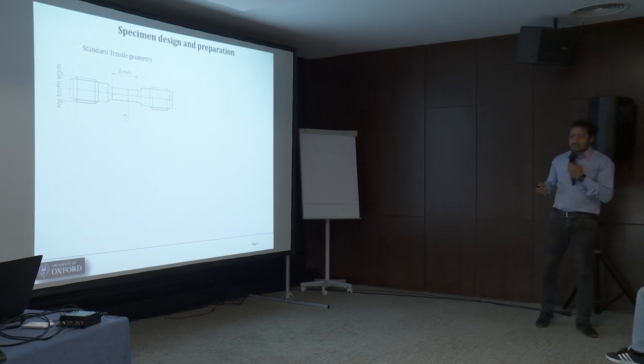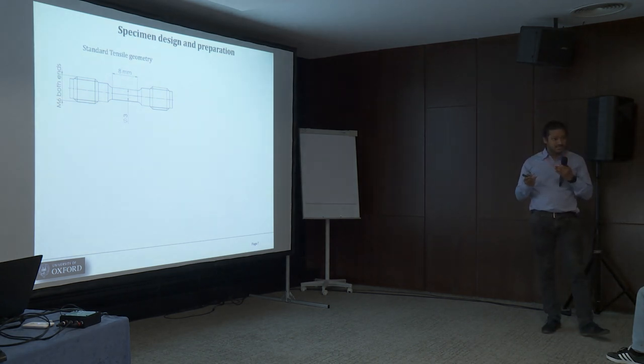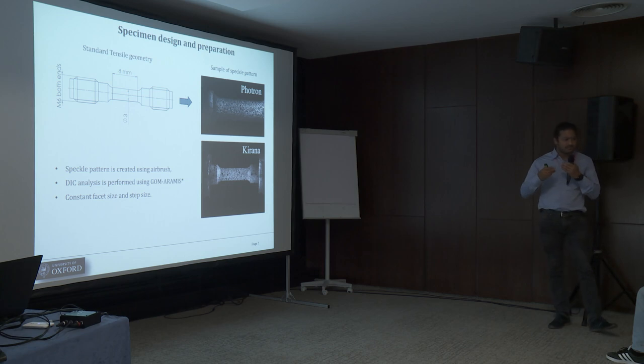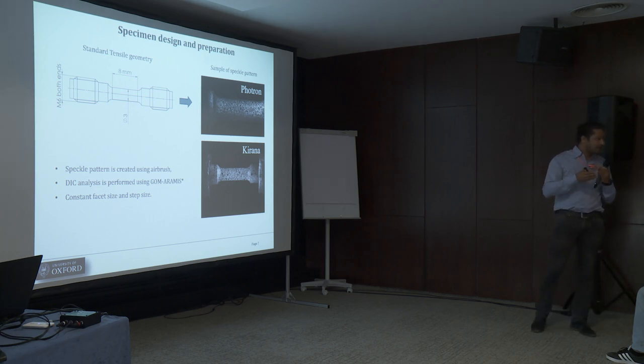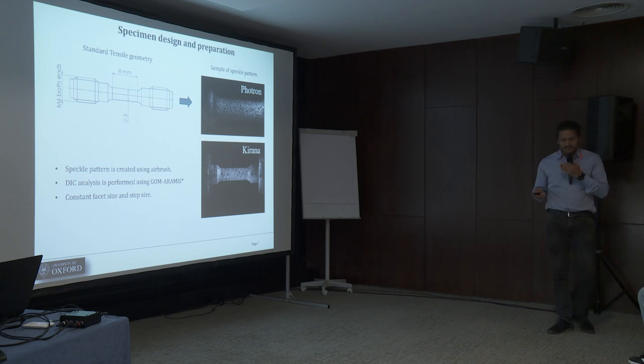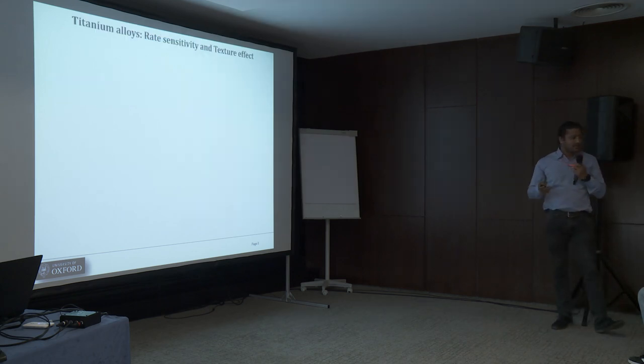For testing, we used the standard tensile geometry from vast experience in the lab — 8 mm gauge length and 3 mm diameter. We created a speckle pattern using an airbrush so we could perform digital image correlation analysis. Throughout all the analysis, we maintained constant facet size and step size to avoid any discrepancy in the analysis.